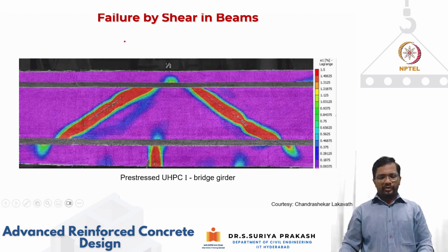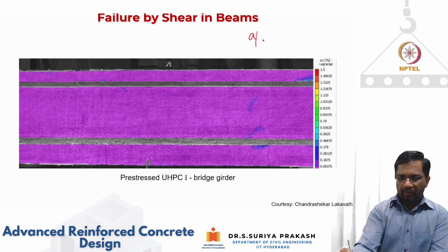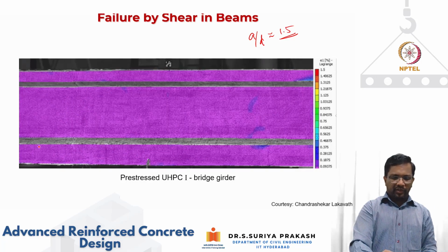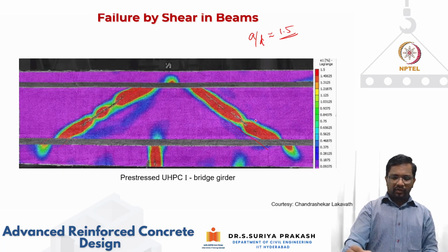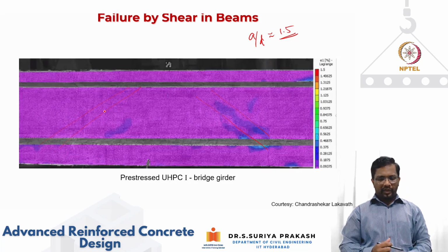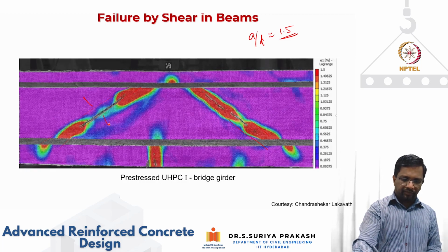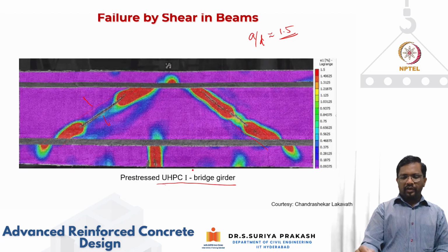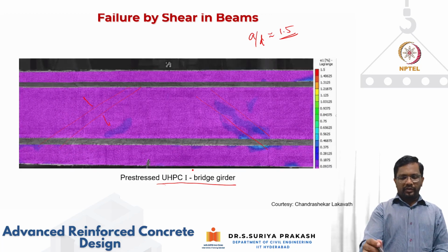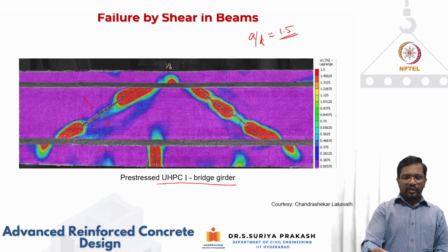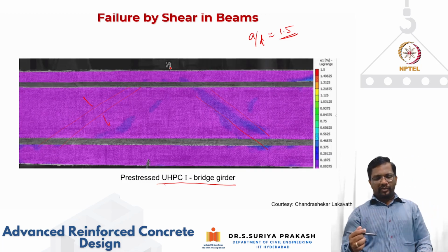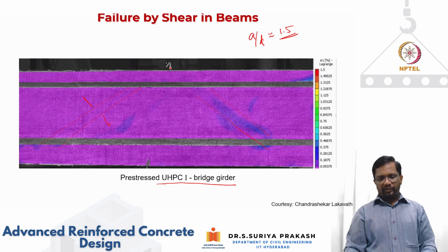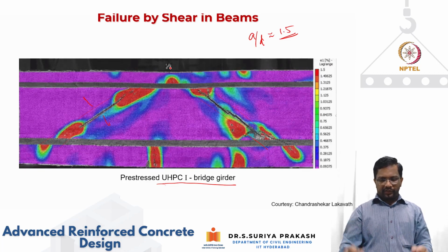So these are some of the beams that we have tested in our lab. You can see here this was an I girder which was tested at a/d ratio of about 1.5. So you have a predominant arch action. You form the strut, and then finally the strut fails by diagonal cracking because of the lateral tension. This is basically a pre-stressed ultra high performance concrete I girder, which we tested in our lab. It was designed to fail in shear to understand how different internal resisting mechanisms are developing. You can see a classical deep beam action, and then finally you have the strut failing in lateral tension.